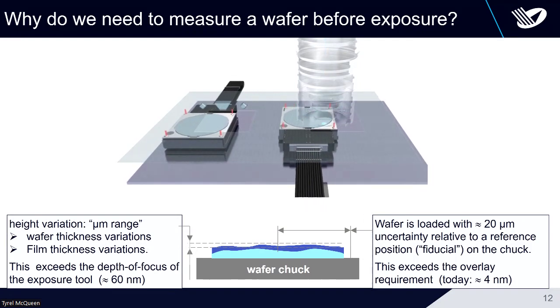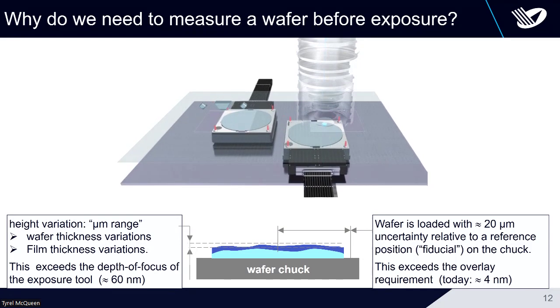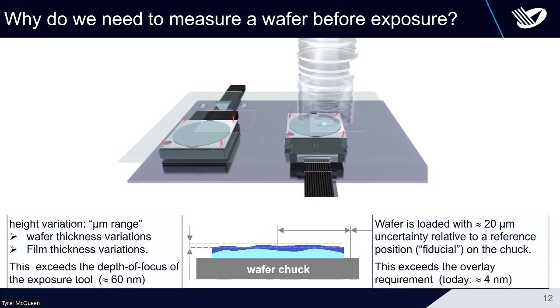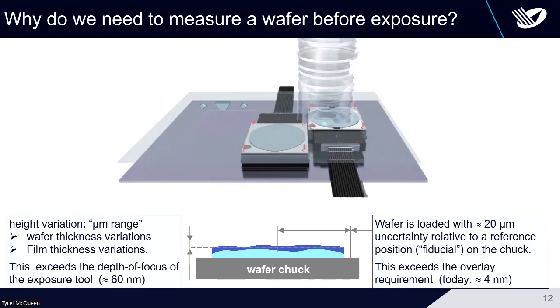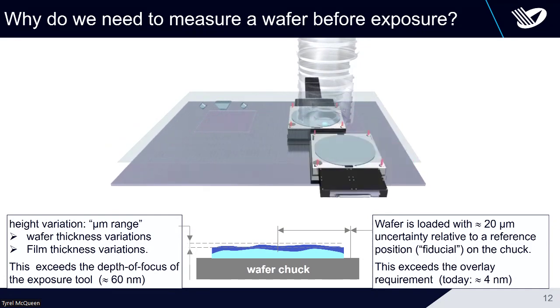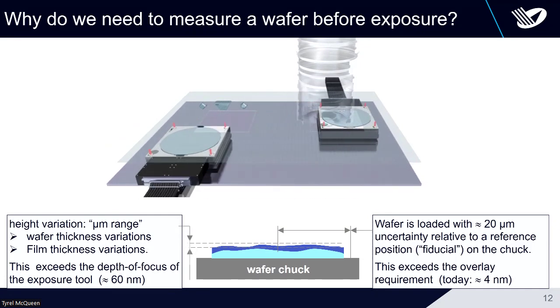Now, why is that actually needed in the first place? It's mainly because there are a lot of height variations. If you put a 30 centimeter wafer on a table, it's not flat. It's buckling and warping like crazy. So that's why it needs to be mapped out. And then there are film thickness variations also, because that is not nearly at the uniformity level of the few nanometers that is needed. So it needs to be measured. Then this information is fed through the lithography column, and the depth of focus can be accordingly varied.